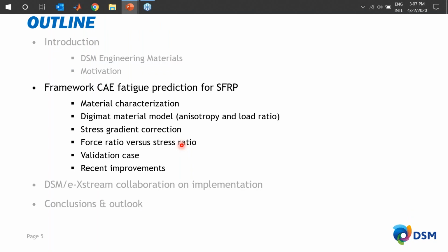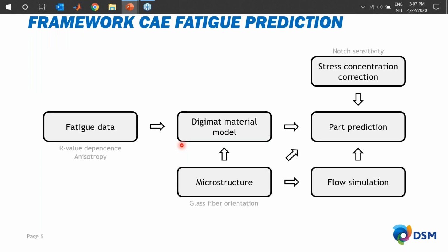So now to the fun part. So let's say the content. Let's look at the framework that we developed. Schematically speaking, it looks like this. If you have the framework for fatigue predictions, then you can imagine that you have to start with some fatigue data. So you have to capture the R value dependency and the influence of anisotropy. But if you have the fatigue data, you have to convert this into a material model. And here we use the DIGIMAT fatigue material model that basically calibrates your material strength in different directions to predict also the anisotropic performance. To do so, you need to have some information on the microstructure.